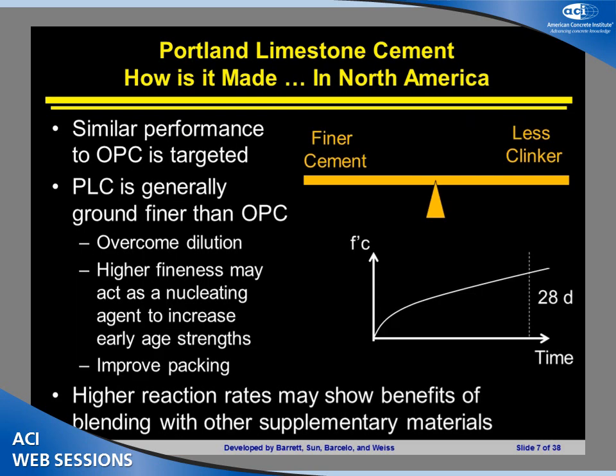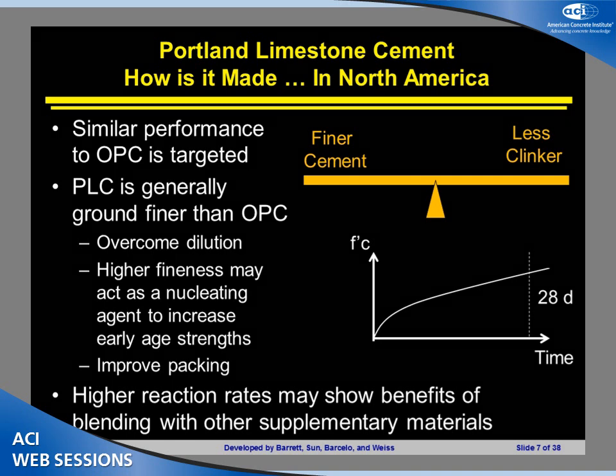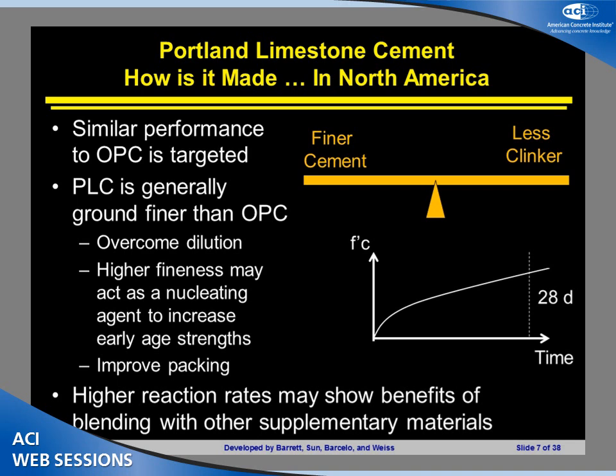One that I will slow down a little bit to talk about is really the how, and I think the how is important here because this differs from what we see in a lot of different applications. In the North American experience, the real thing that I will keep coming back to is we're targeting similar performance to the OPC. So we're using less clinker. By using less clinker, we're diluting the clinker a little bit, and typically what we're going to see is the cement is ground finer. So in general, Portland limestone cement is going to be ground finer than the OPC. One of the reasons for this is to overcome dilution.